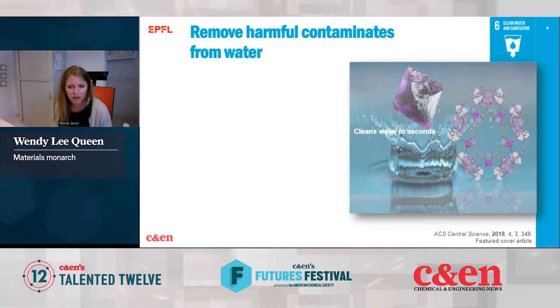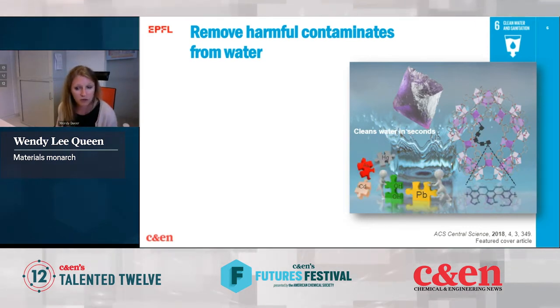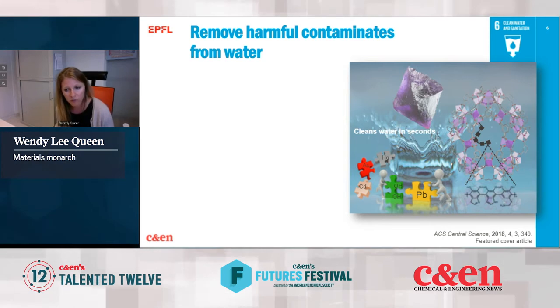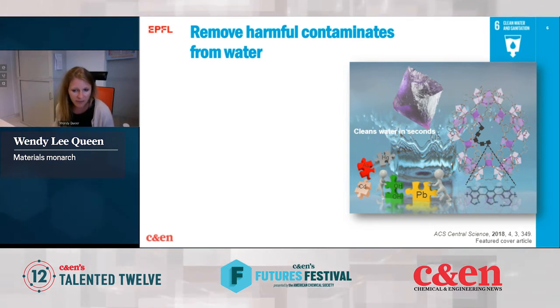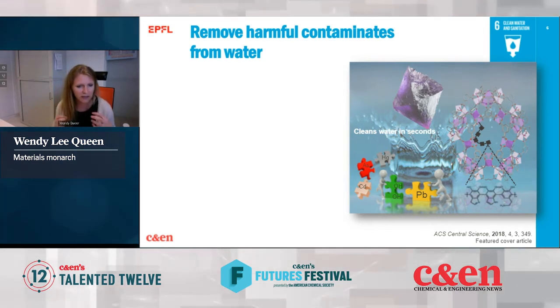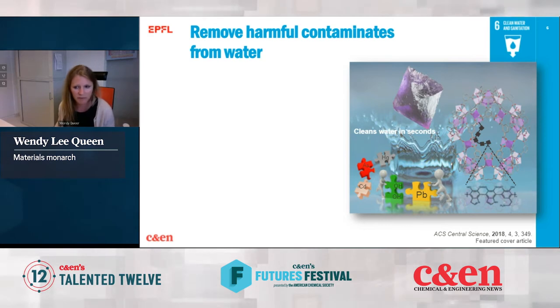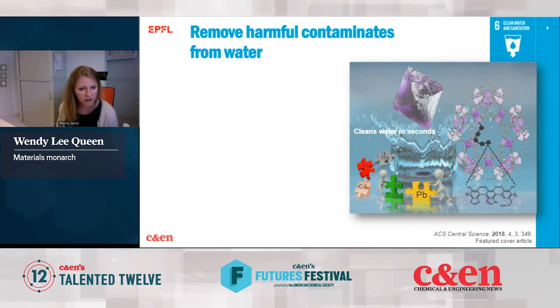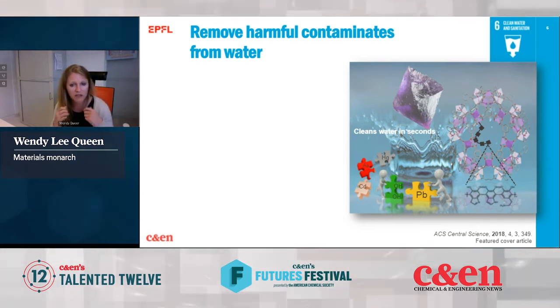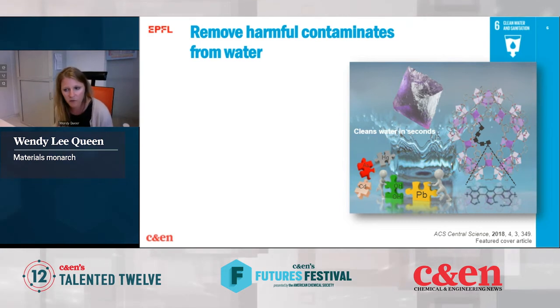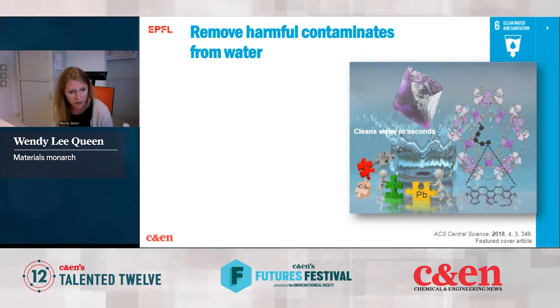We've done something a little bit unique. We've learned how to append short-chain polymers inside our MOFs, and what you'll note is on this polymer backbone, it's really got some nice functionality that can complex, for instance, heavy metals in water. The key is that these short-chain polymers basically enhance the MOF performance quite significantly. And so that's what I'm showing you here.